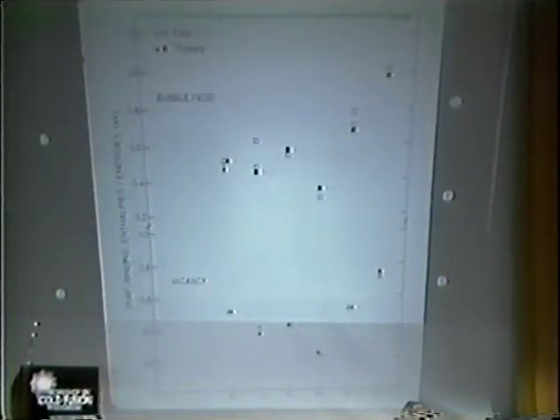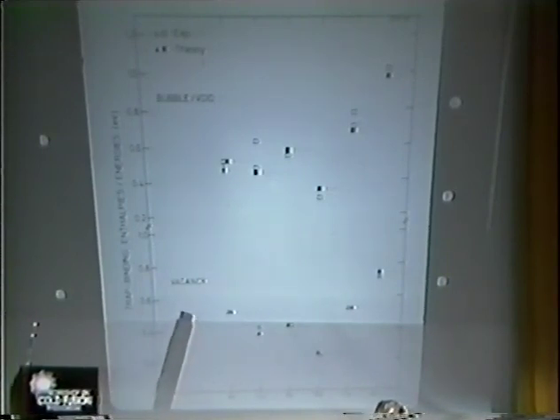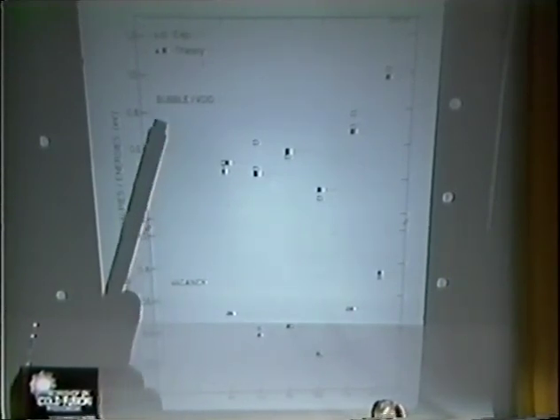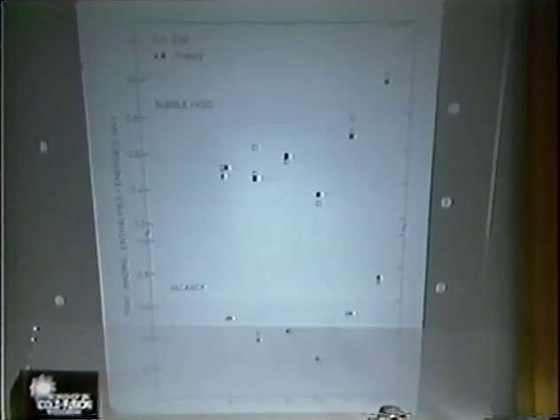If we now show the trap strengths we have extracted here for a number of different metals and compare that with the effective medium theory, the first thing you can see is that that's for a single hydrogen at a vacancy, and that's for hydrogen bound to a void up here. We can see that the theory is capable of reproducing all the trends observed, and there's even a very good absolute agreement, which is maybe a little bit surprising. One thing that is very evident here is that palladium has fairly low trap strengths.